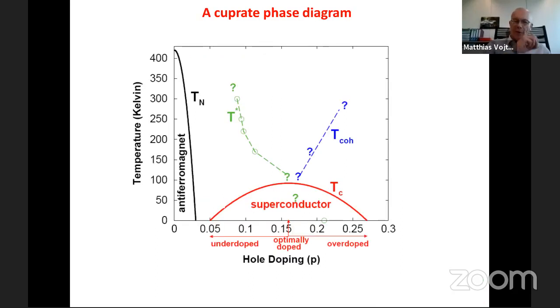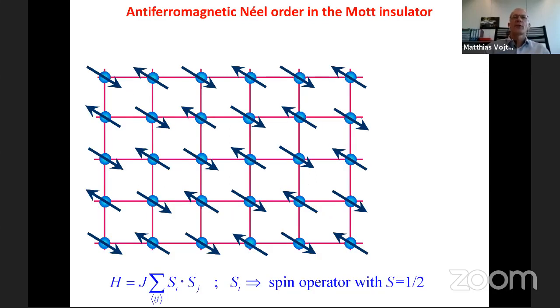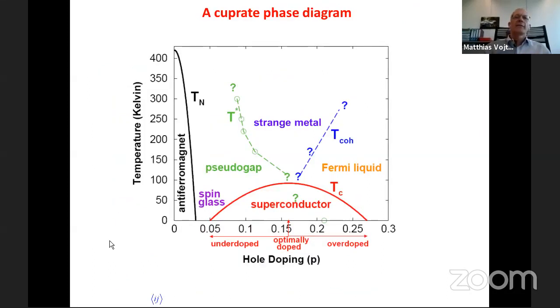So here is a typical phase diagram of cuprate superconductors. This shows temperature on one axis and chemical doping on the other axis. The systems start out, in the undoped case, as a half-filled Mott insulator. And the physics is mainly on the square lattice. So what we start with is a square lattice antiferromagnet. You've seen this picture before. That is magnetically ordered. And then upon moving to the right-hand side, we add charge carriers to the system, either electrons or holes. This is what first destroys the magnetism and then brings about superconductivity with a rather high TC of 100 Kelvin or higher.